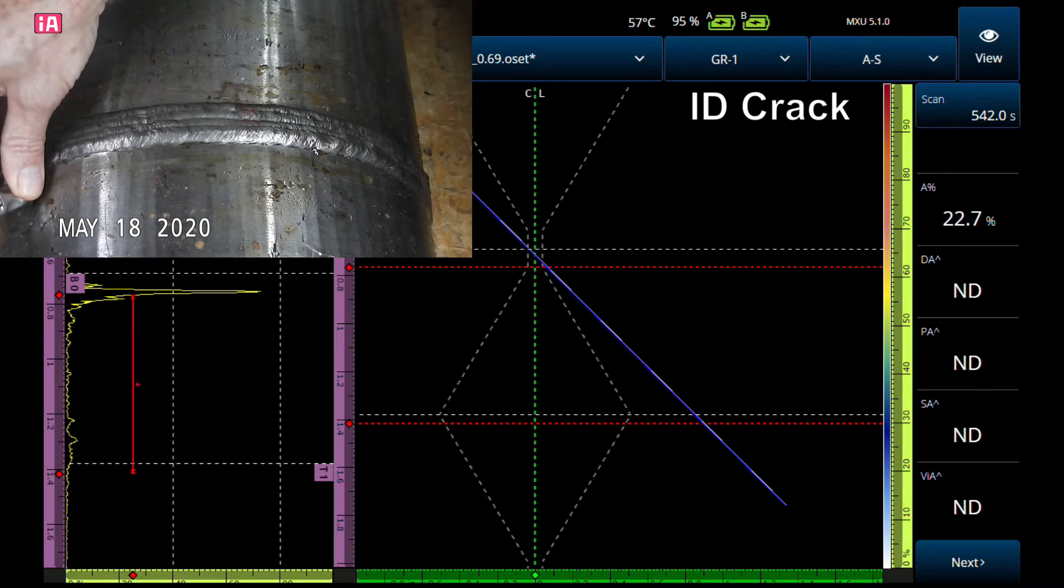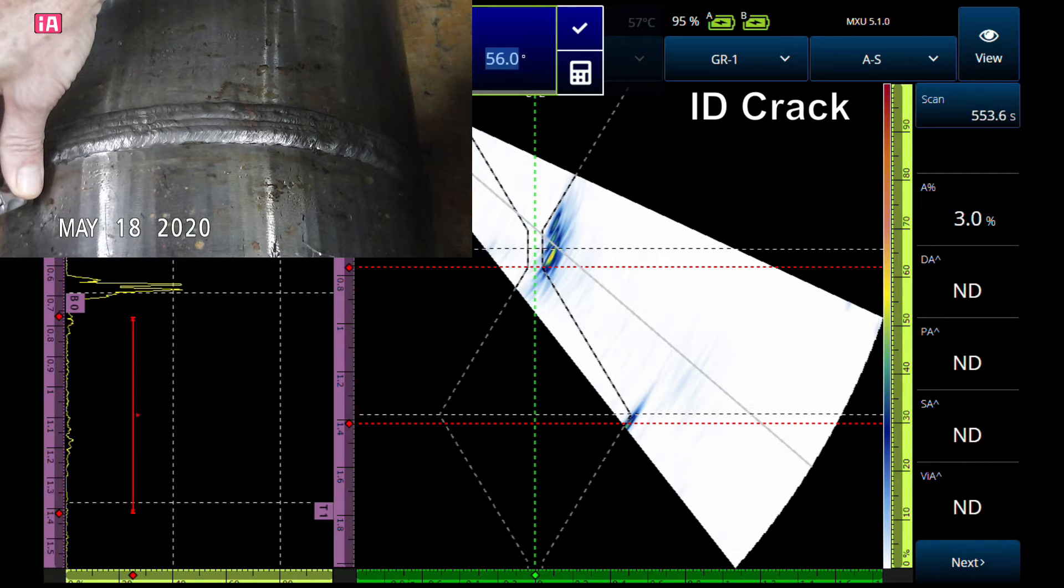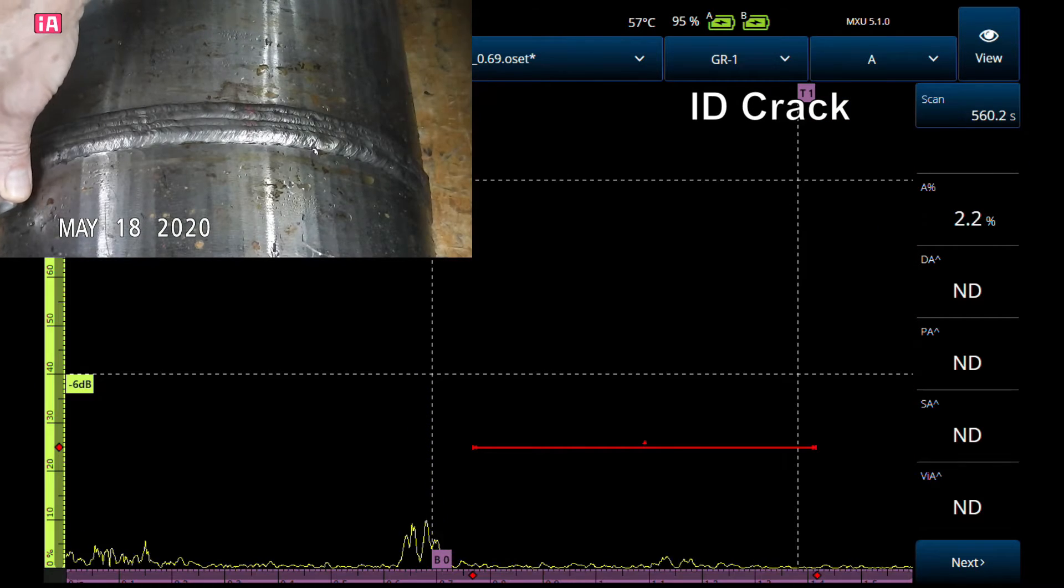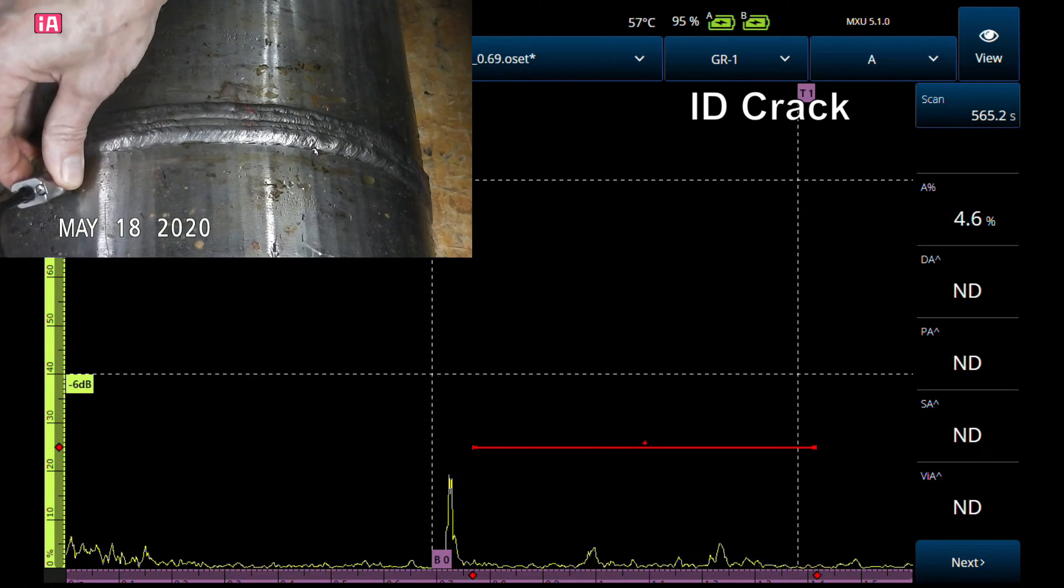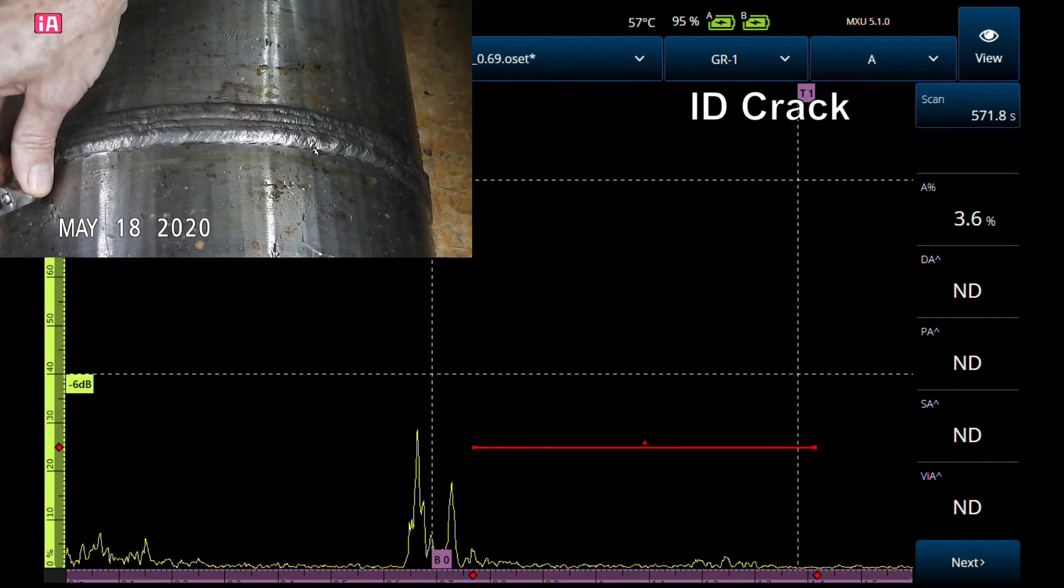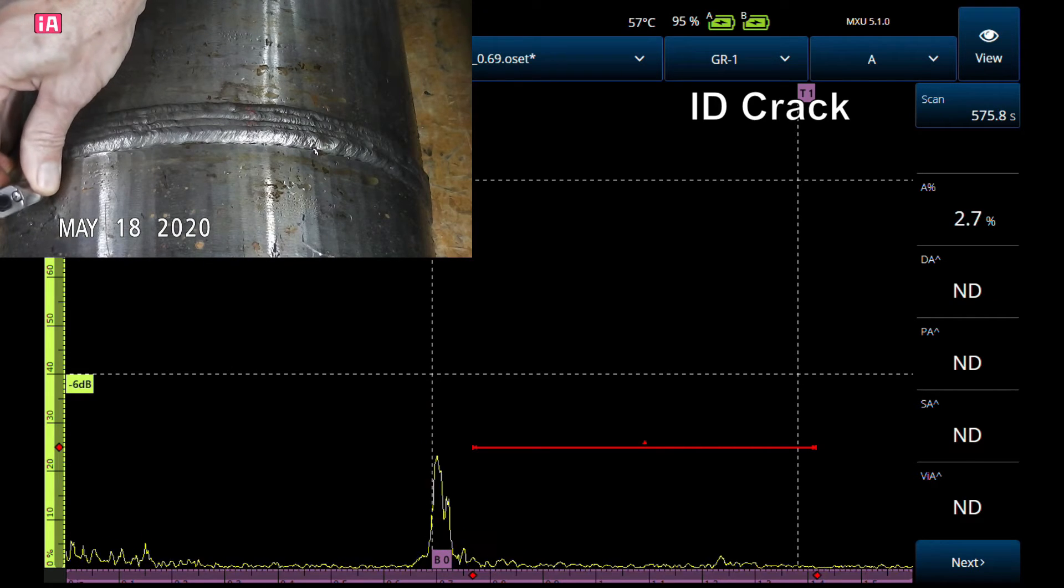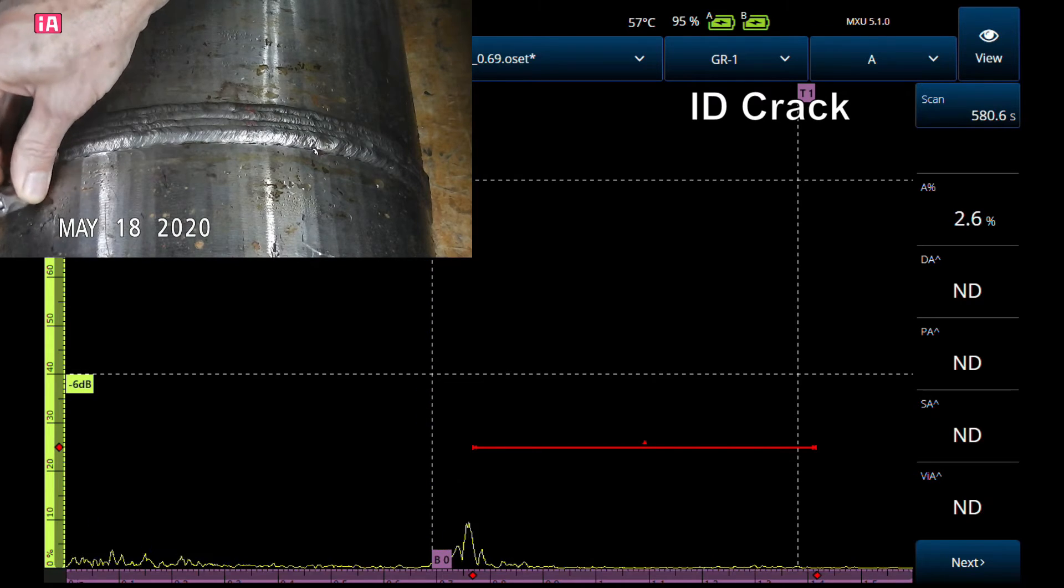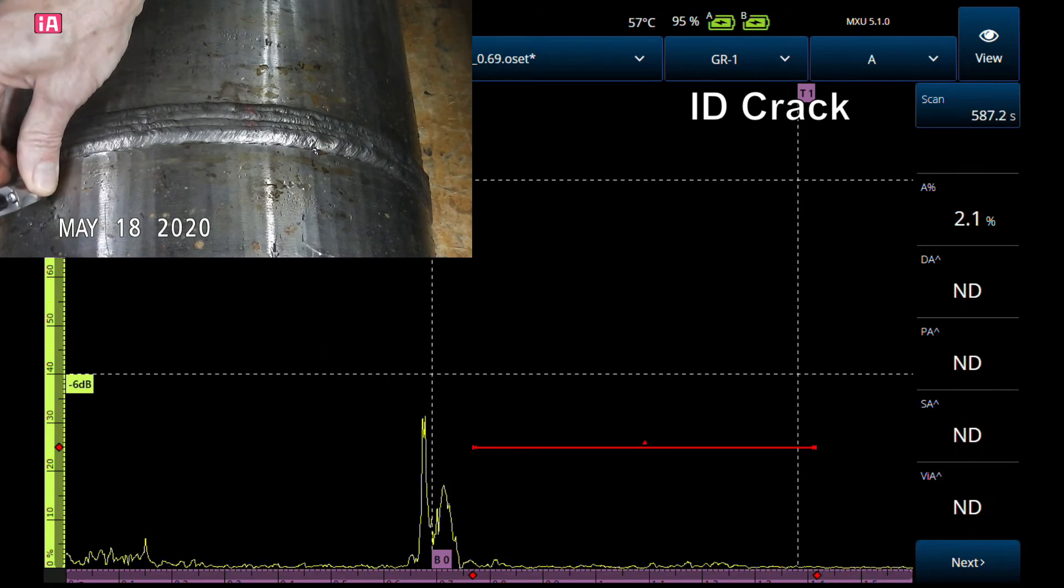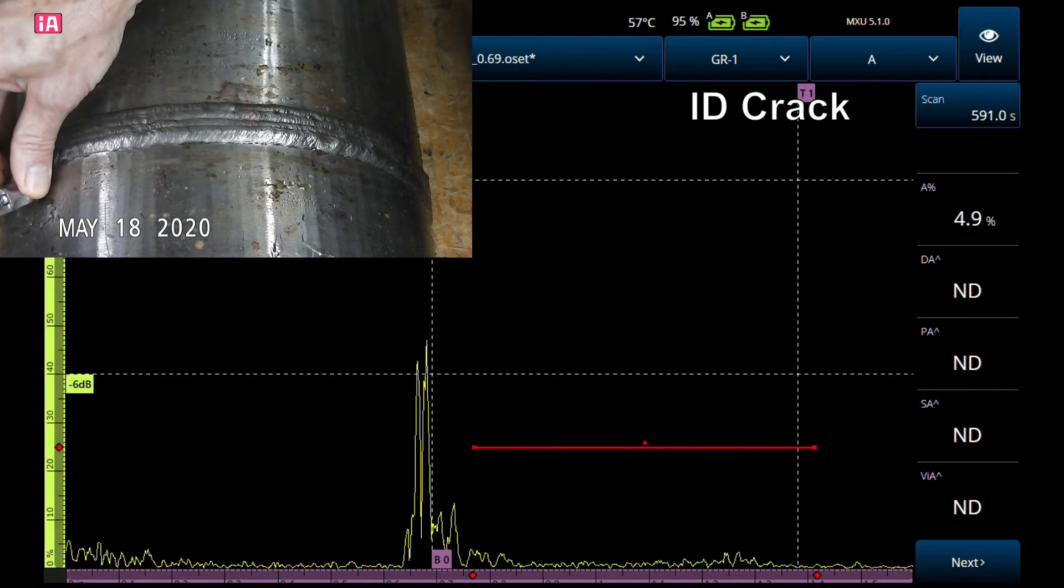The reason that's coming up right there is because of the angle that's on right now. Let's change that angle a bit. Now it's coming up in front of the ID—very wide, a lot of facets. A crack has a very rough surface so it can reflect a lot more sound as you're skewing it than what lack of fusion does. It's another way to tell the difference between cracks and lack of fusion. So that is the root crack.